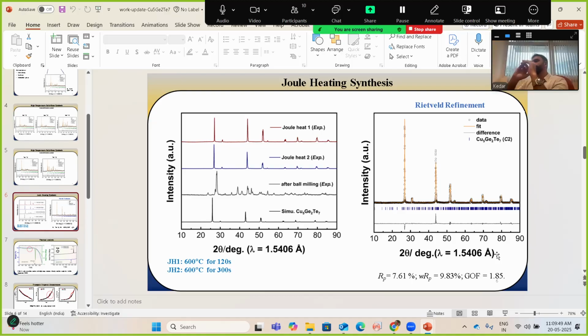Yeah. Because forget about the after ball milling, right? Let's go to the Joule heated compounds. They all move towards this side, that is higher 2 theta. What that means is that the lattice is shrinking, because 2 theta and D spacing are inversely correlated. Which means that for some reason your lattice is shrinking. That could be because of a nano inclusion or a doping. Germanium telluride is possibly smaller than this. That could be the reason. That's why I thought, do you have germanium telluride?